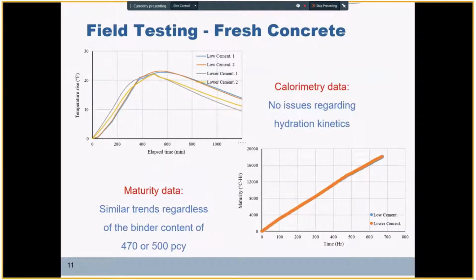Two samples were tested for calorimetry per mixture. No abnormalities were observed with the calorimetry data. There was a slightly higher heat of hydration with increased amount of cementitious material from 470 to 500, but totally the same trends, and no problems that could be attributed to the cementitious materials content.